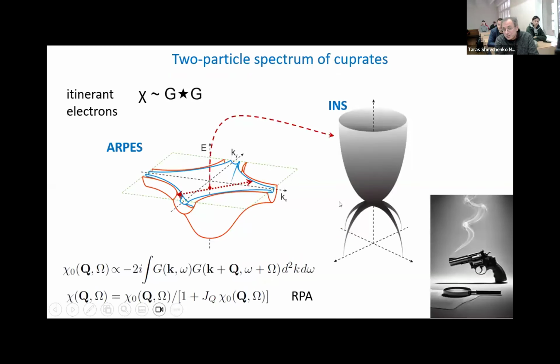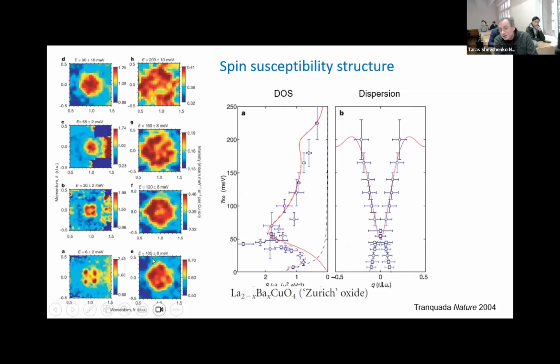And this actually helps to explain this smoking gun experiment. It would be a smoking gun experiment if the samples were better, or the statistics were better maybe. But anyway, it shows, I think, this correspondence: this is a two particle excitation. This means that electrons from here could go to unoccupied states here, and this is the so-called electron susceptibility. And if they flip the spin, then you have this spin excitation. You can calculate this expected spectrum of spin excitations from the known electronic band structure, and you can measure it and see that it really follows our expectation.